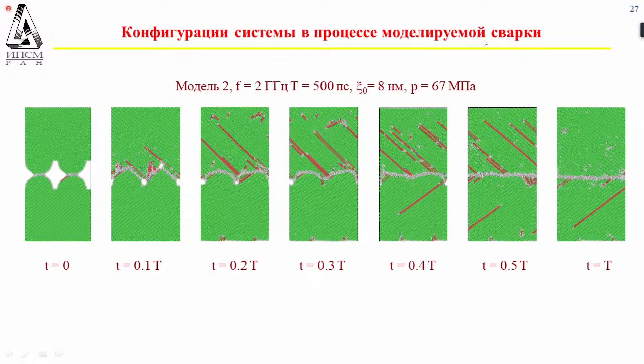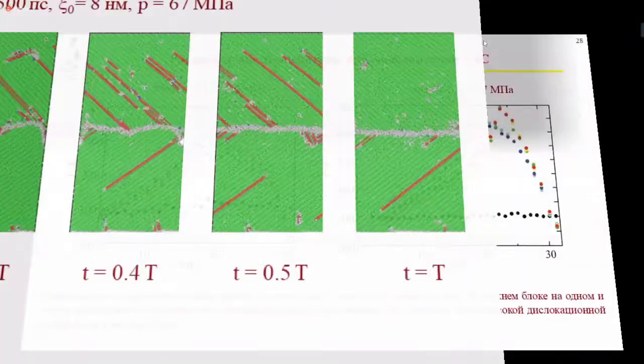At the first stage, we can observe intensive dislocational activity, and it's a high activity. And in the following, it will go through because they are the boundaries of the grains. And we can see a higher elasticity in this zone, in the area of welding, and a faster closure of pores.